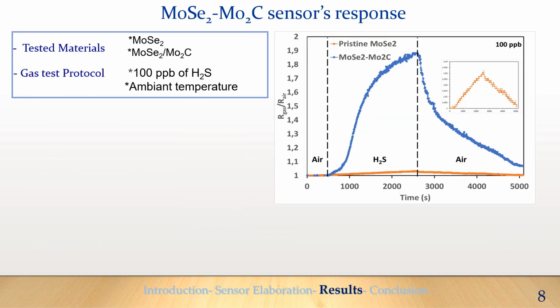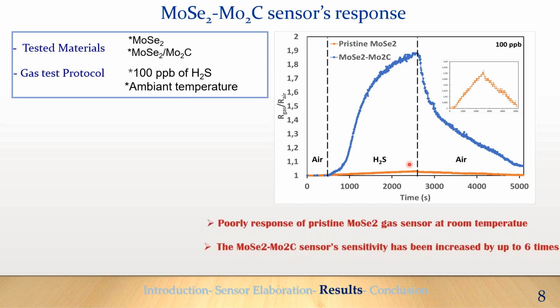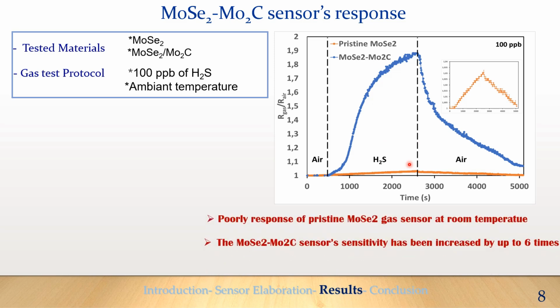To examine the gas sensing performance of the hybrid sensitive material, two sensors based on pristine MoSe2 and MoSe2-Mo2C were exposed alternately to 100 ppb of H2S and to air at ambient temperature. As shown here, the MoSe2-Mo2C enhanced the sensitivity to H2S compared to pristine MoSe2 by up to 6 times.